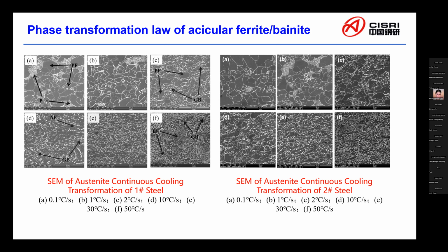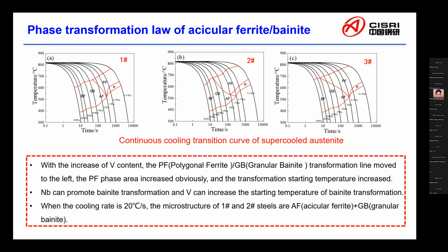When the cooling rate comes to 10 degrees centigrade per second, main microstructure are granular bainite and acicular ferrite. When the cooling rate is 50 degrees centigrade per second, main microstructure are bainitic ferrite and granular bainite. Grain size is finer along with the increase of cooling rate. Phase transformation law is obtained by means of a continuous cooling transformation curve of supercooled austenite.